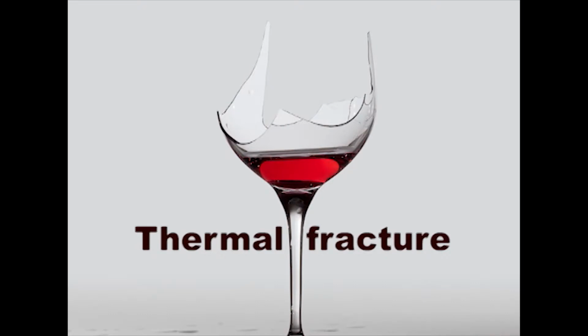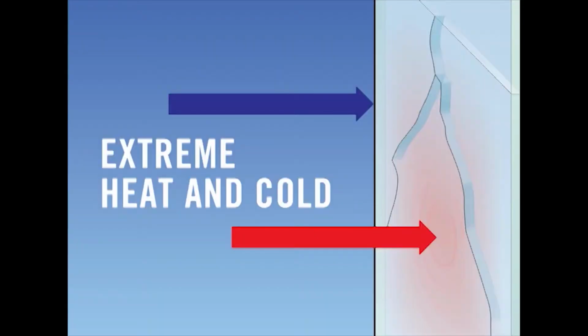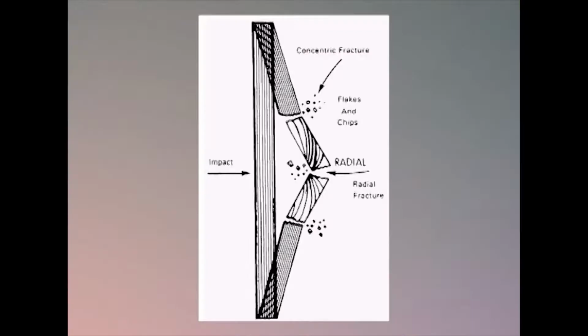If very hot liquids are poured into cold glass, or a very cold liquid is poured into hot glass, a thermal shock is produced, leading to fractures. These occur in the bottom of the container, around the circumference, with no or very rare surface markings, resulting in fracture along the long axis of the container. Then come the impact fractures. These generate the most complex stresses of any type of fracture.